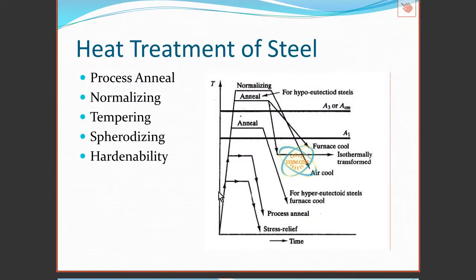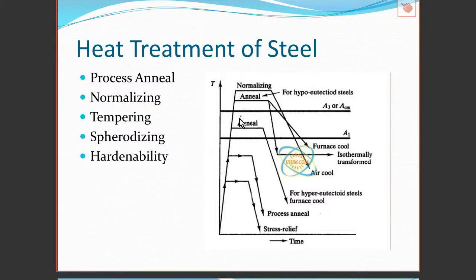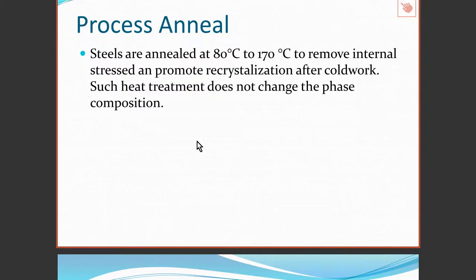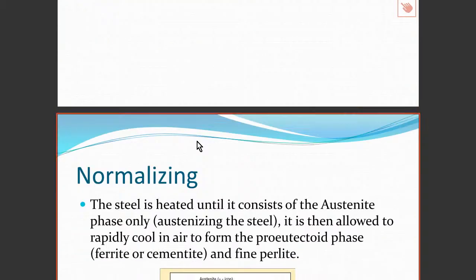These processes are shown differently — as you could program a furnace, they just tell you the temperature at which the material is kept for a given time interval. We see we ramp up to a temperature, we have a soak zone, and then we cool down. At lower temperatures we're just using a stress relief; slightly higher, a process anneal, which just removes the effects of cold work without changing the phase composition. At higher temperatures we do start to change the phase composition.